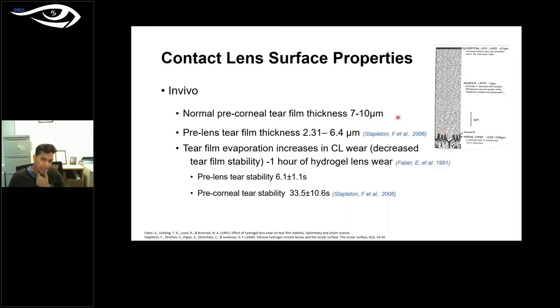The moment you place a contact lens, it actually reduces the thickness by about half. So the pre-lens tear thickness is measured to be around 2.31 to 6.4 micrometers. Obviously, given that the pre-lens tear film is so thin, there is greater evaporation on the surface of the contact lens even within 1 hour. So the pre-lens tear film stability is measured to be 6.1 seconds, whereas if there is no lens, the tear film stability is about 33 seconds, which is quite long. So by putting a lens, we are basically giving faster breakup time over the contact lens.